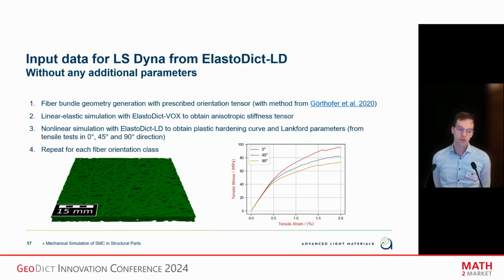This could also be done for injection molded materials. Then you would not have this mesoscale model as a structure, but just the regular structure where the fibers are resolved. And actually there's even an advantage compared to experimental characterization, because in these virtual experiments, you know exactly the fiber orientation which you used for your calibration experiment, which is not the case if you extract samples from plates or components. You can never be sure which orientation you are actually testing. In this case, with virtual structures, you know it exactly because you prescribe it.